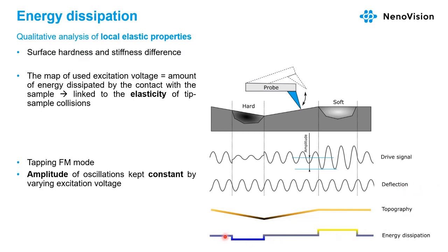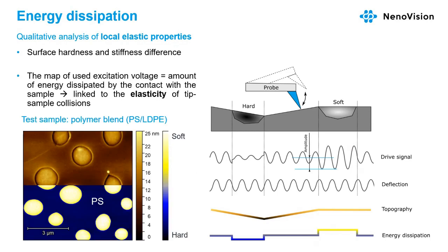So then the harder part of the image is darker because it has a smaller drive signal used to maintain the same frequency, same amplitude, and in the opposite way, softer is brighter with a higher amplitude of the driving signal. So we see again the polymer blend of the brighter, softer part and the darker, harder part.